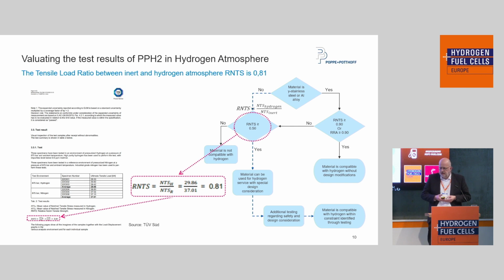Evaluating the test results of PPH2 in hydrogen atmosphere, it's at the end a tensile load ratio between inert and hydrogen atmosphere, so-called RNTS. And we have here an excellent value of 0.81. 0.5 would be the limit, and 0.81 is much above that. And so this material, according to this test, can be used.